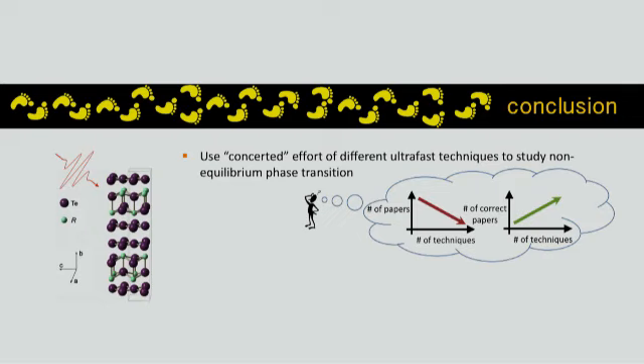As for the power law, there is some theory saying that domain annihilation recovers with a power law. I don't think from our short time probe we can differentiate a power law from an exponential fit. There are studies of other CDW materials which look at, for example, nanosecond recovery, which they do fit with, for example, a square root of time power law recovery.